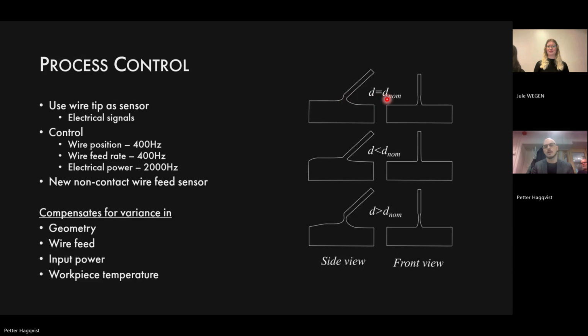This is the nominal process state, because we can be quite sure that if it looks like this, the wire is not interacting with the unmolten substrate, which you see here. The middle portion shows that the wire is actually too far down. So there is a significant risk of the unmolten wire protruding through the melt pool, interacting and exerting a force onto the substrate, which would typically lead to an increased risk of a lack of fusion.